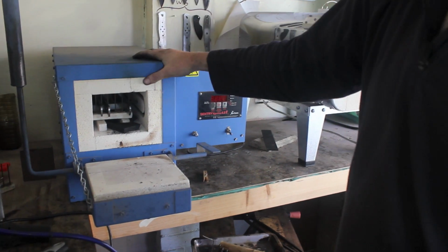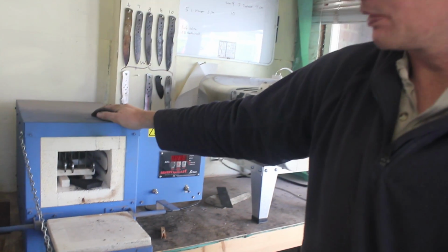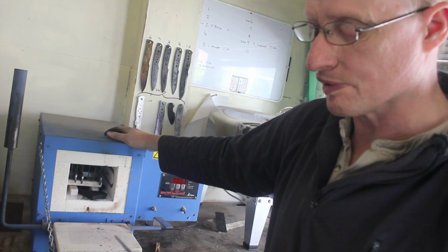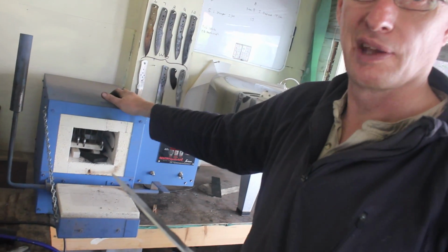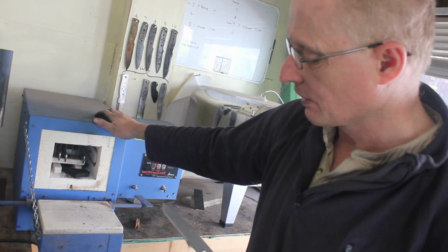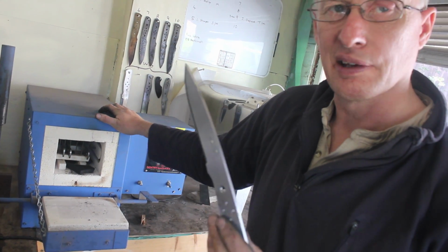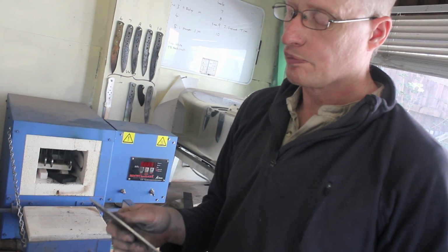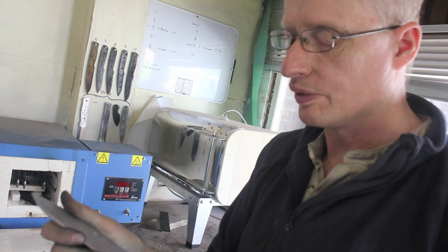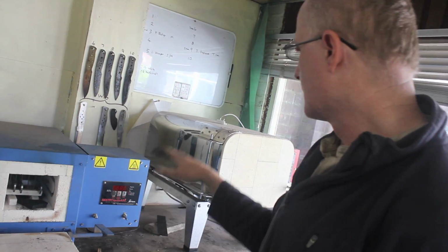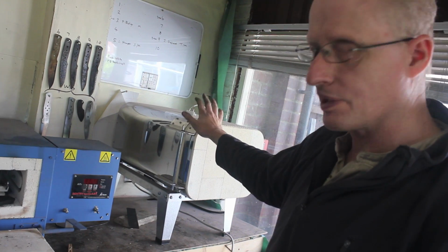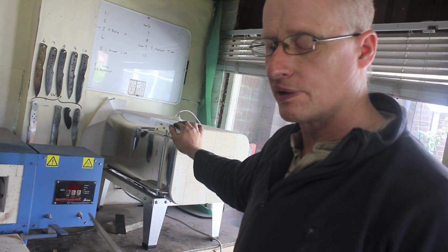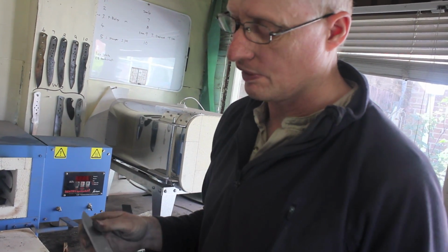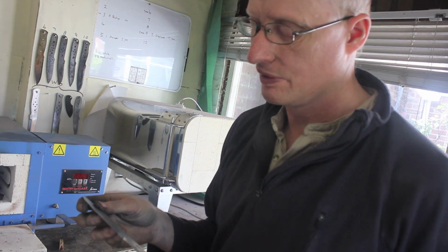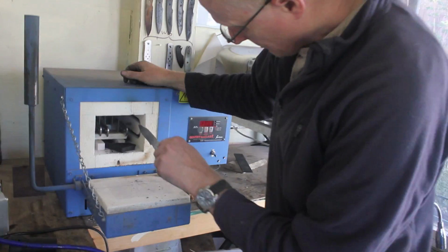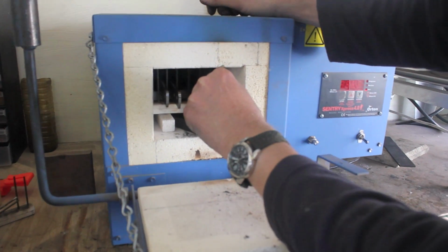Now this one will go to a very high temperature, to above the critical temperature, the low end of the critical temperature, and then I'll remove it, quench that, and whilst they're still hot, or too hot to hold really, they'll be going into the tempering oven, which will be preheated at a much lower temperature for tempering cycles. Okay, so in we go. Put them into that slot there.